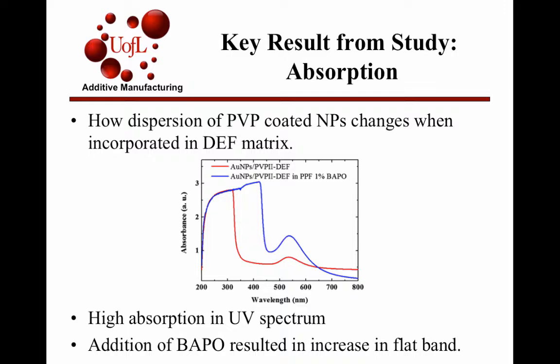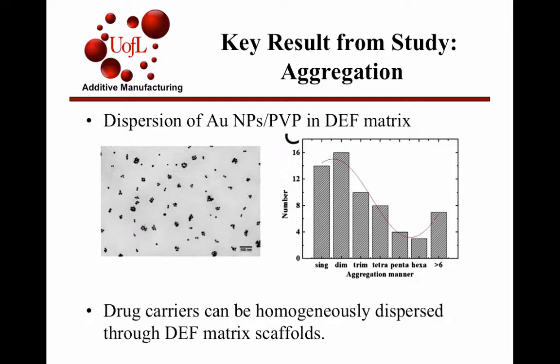This is a picture of the nanoparticles in the DEF matrix, and it showed how the dispersion was fairly homogeneous. This is what they were looking for. They were satisfied with the results. One of the comments they made is that the images were hard to get because of the wavelength and how it was acting: it started to cure as soon as they took the images. So it was difficult to get a good image, but overall they were very happy with how homogeneous it was, and said this would definitely be good for the applications they were using.